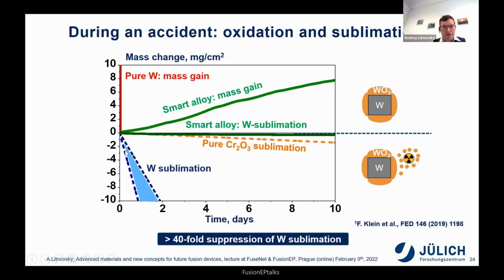And this is actually shown here. It is a much less intensive process. You can see the sublimation of tungsten layers within this limit. Look at the sublimation as a negative mass of the smart alloy. It is essentially zero. Well, without cheating, we cannot detect here the sublimation of chromium, but it will not exceed this line. So you see the factor of 40 suppression of tungsten sublimation by these fantastic nanomaterials.